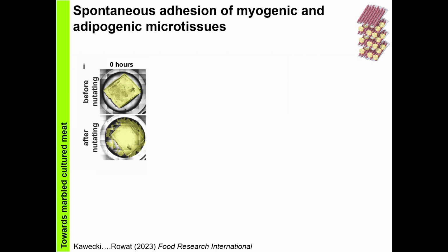And what happens, you see, is that the adipogenic microtissue sort of falls off. It's displaced from the myogenic microtissue. And you can see this because the yellow now is showing you where the fat microtissue has been displaced to. So this is at 0 hours, so you wouldn't expect that there would be much attachment between the two different